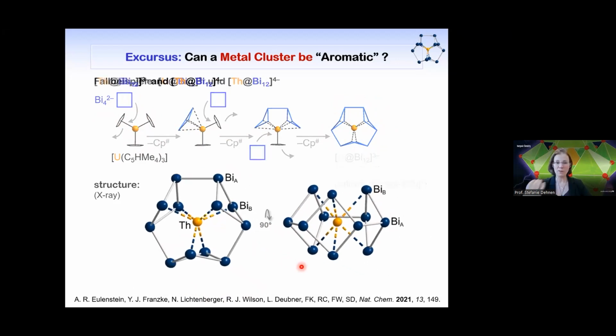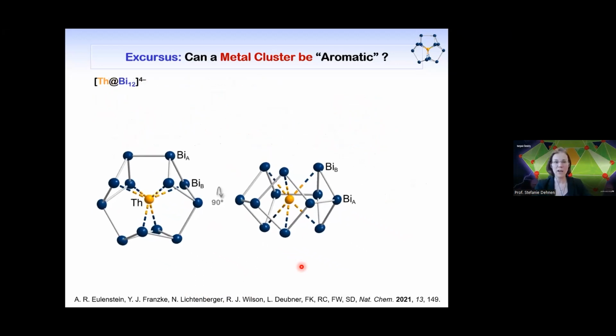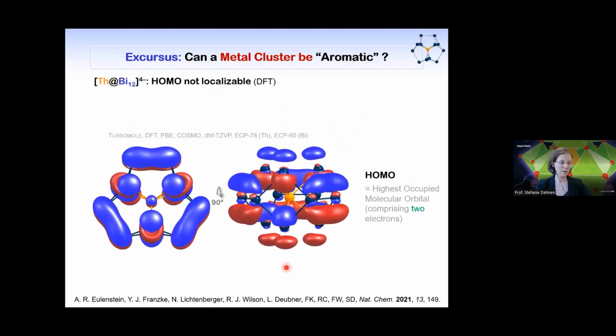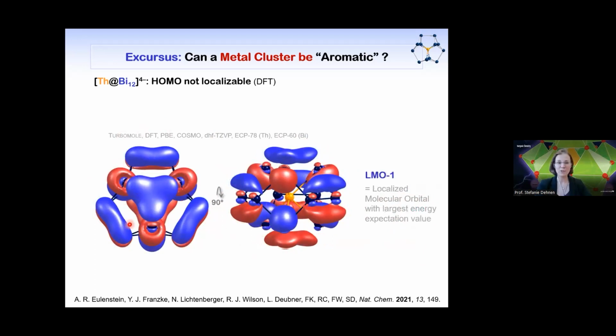And to find out about aromatic properties, what you have to do is look after the molecular orbitals. And what I'm displaying here is the so-called HOMO, so the highest occupied molecular orbital that is hosting exactly 2 electrons. And you see that this is the thorium atom inside. So you see that the thorium atom does not contribute, but all bismuth atoms contribute to this HOMO. And this caught our interest. We thought if all of these bismuth atoms are involved in one orbital, maybe it's not localizable, and so you can look after ring currents. And this is actually what happens if you try and localize this.